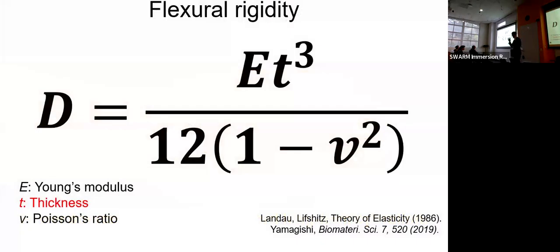Then we are more focusing on how to make very, very thin electronic device systems. Here I would like to show you a very important equation, the flexural rigidity, to explain why thinness is a very important parameter. Here, flexural rigidity D is determined by using these equations. E is the Young's modulus of the material. T is the thickness of the films. So you can easily understand that if we reduce the thickness, it can be effective to reduce the flexural rigidity values. So we try to reduce the thickness of the whole device systems to make softer device systems.